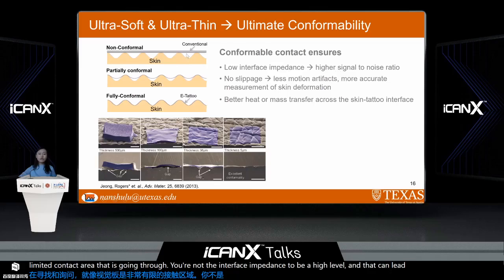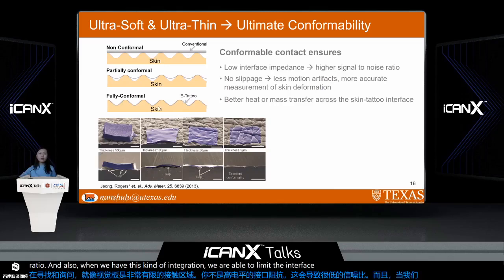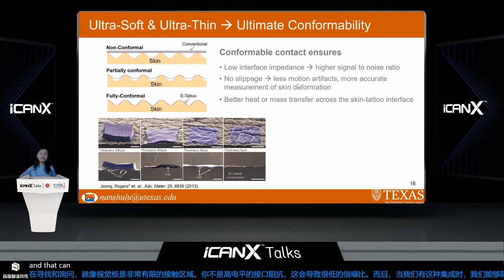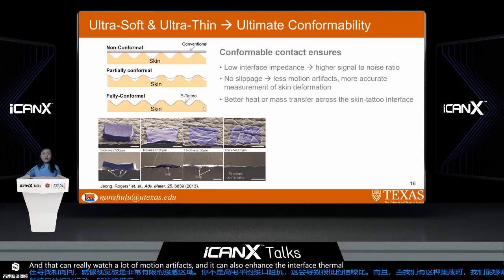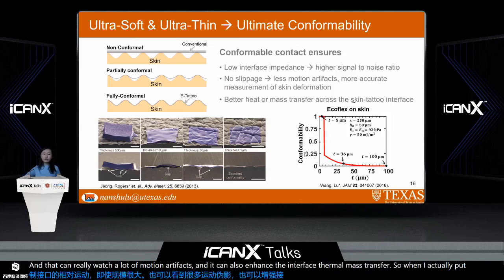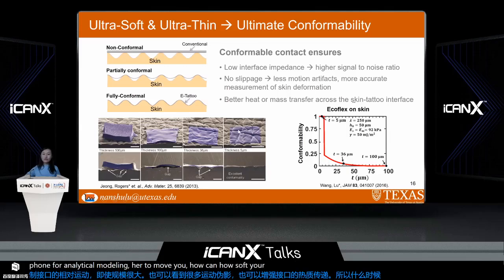And also when we have this kind of integration, we are able to limit the interface relative motion even when the skin is under large deformation, and that can minimize a lot of motion artifacts, and it can also enhance the interface thermal or mass transfer. So we actually performed a lot of analytical modeling to review how thin and how soft you need the e-tattoo to be to achieve 100% conformability.